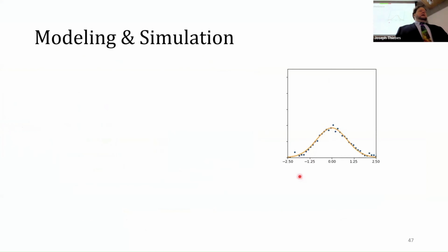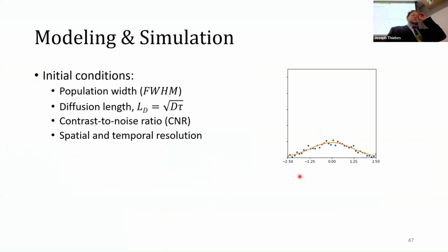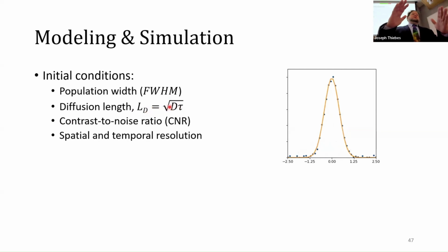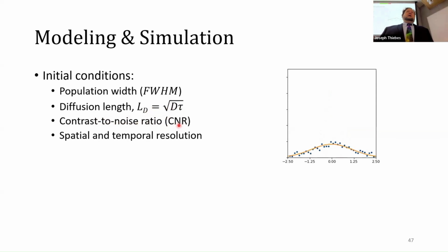So to do the modeling, I generated a series of time-evolved Gaussians with a given set of initial conditions, and then I added noise to them. Then I fitted them and compared the fit to the parameters that I input. We start with the initial conditions: the population width, and the diffusion length, which combines both the diffusion coefficient and the lifetime into one parameter. We can use that generalization so that any combination of these two that multiplies and square roots out to the same diffusion length will give us the same results in terms of how quickly the contrast is lost in the signal. We start with an initial contrast to noise ratio, which is the peak height at time zero relative to the standard deviation of the noise. And then we have parameters for spatial and temporal resolution: how many pixels we have, and how many time frames we have.